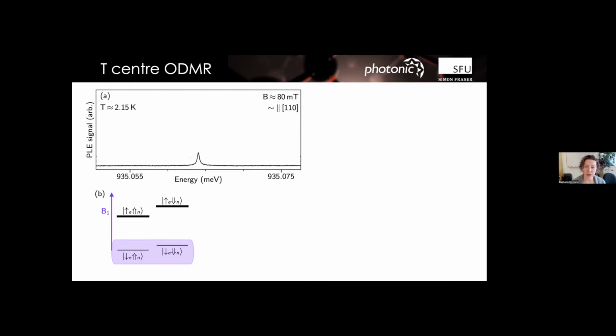Okay, so now that you have that spin photon interface, you can go and try and drive it resonantly. And we were very lucky to find out that these things can be driven resonantly, kind of indefinitely. They don't seem to blink. You can just drive them and they always return. And that's a big difference between the T center and some of those, like the G center in particular, that thing bleaches. So I was really happy to hear that you don't seem to be able to photoionize. And you don't seem to have too much Auger recombination, but that's not for this slide, that's a different conversation.